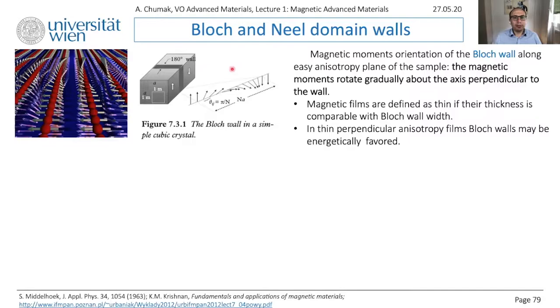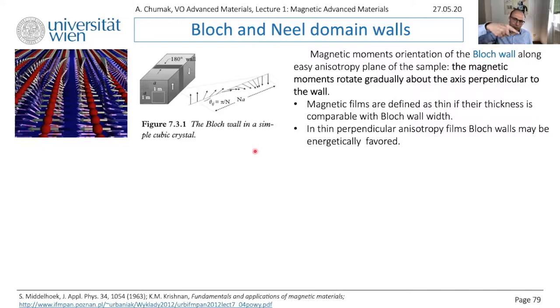The question is how magnetization changes from one direction to the other. Since it is typical for bulk materials or thick films, shape anisotropy — which we discussed — always wants to keep spins in-plane. But since we don't have thin films here, we have a bulk, so magnetization simply rotates in the plane of the domain wall. You can say that the magnetic moments rotate gradually about the axis perpendicular to the domain wall.